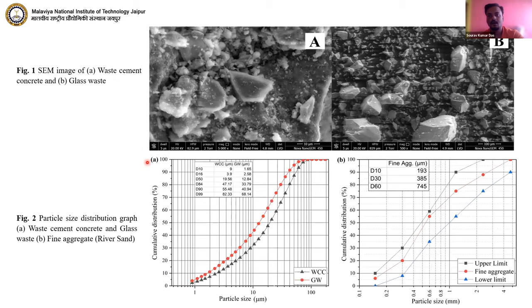So coming to the raw material, here are the SEM images. The left one is the image for your waste cement concrete, and the right one is the glass waste. You can see the particle size after grinding is mostly irregular in shape, with a high level of anhydrous cement particles present in the waste cement concrete particle. Whereas in the particle size distribution graph, you can see that your glass waste has a higher particle fineness than the waste cement concrete.